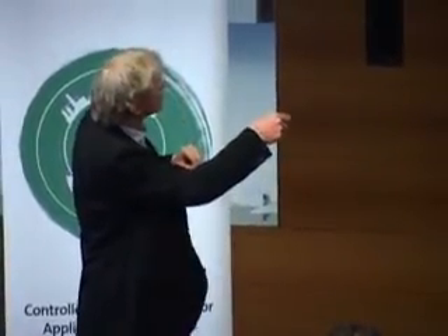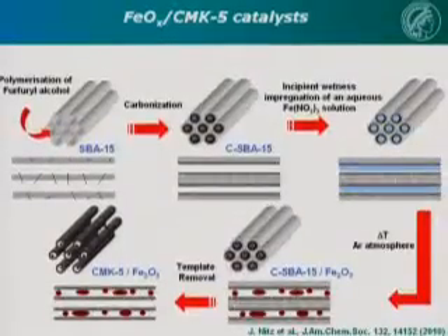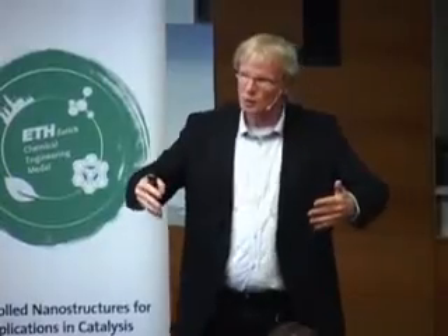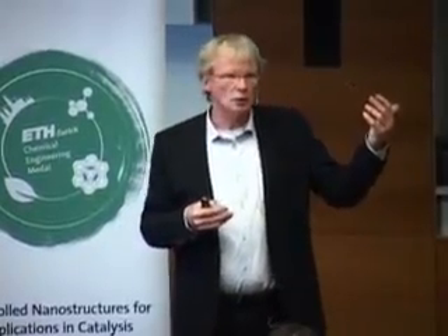So what you see here is tubes of silica and holes in the center of them. The holes here, size scale maybe 6 nanometers approximately, wall thickness maybe 2 nanometers, and you structure this by surfactant liquid crystals. Then you impregnate the inside of these tubes with carbon. You put a precursor for carbon in there. You can use many precursors. Furfuryl alcohol is what we normally use that polymerizes easily.